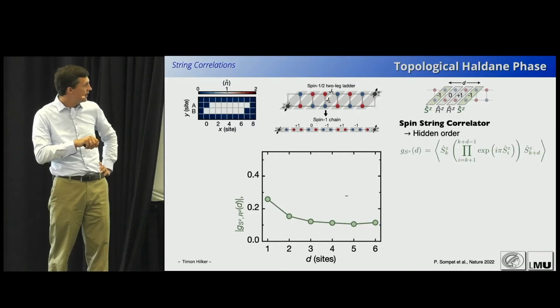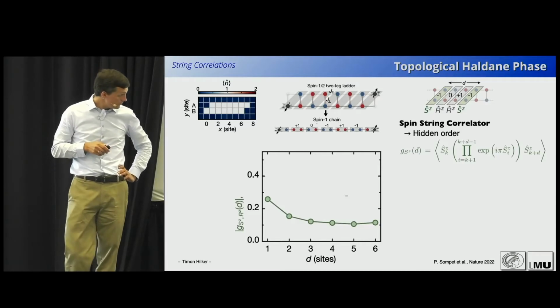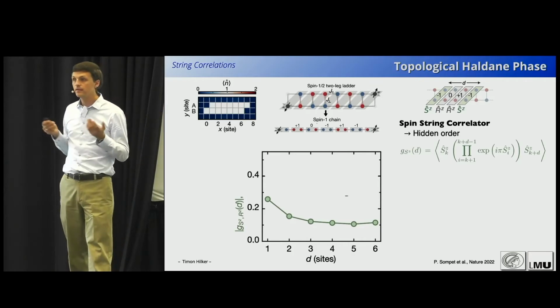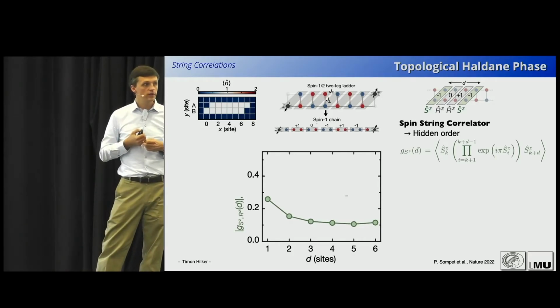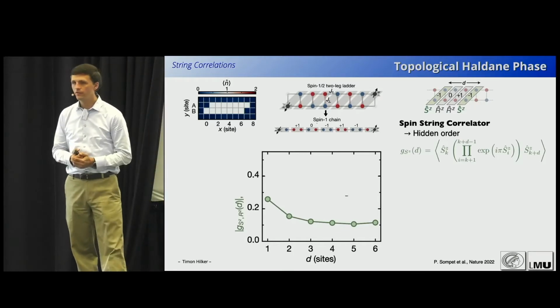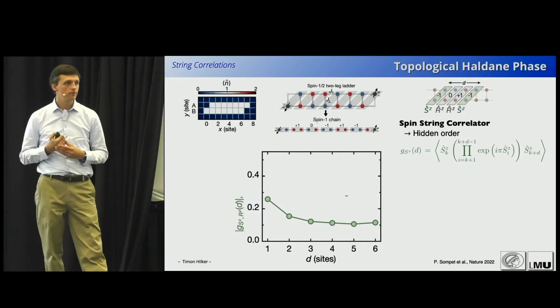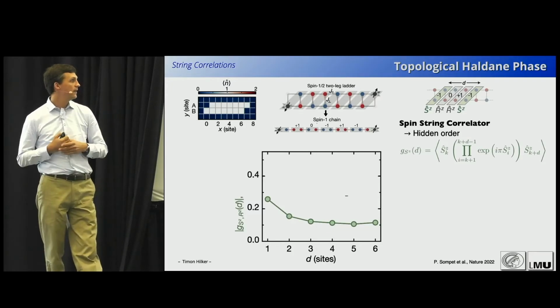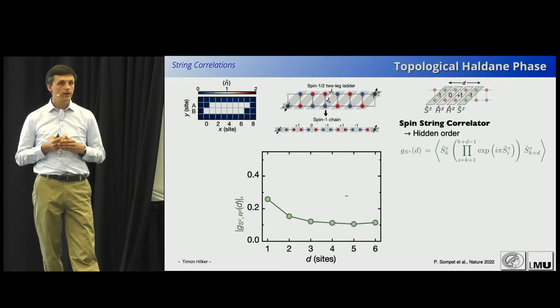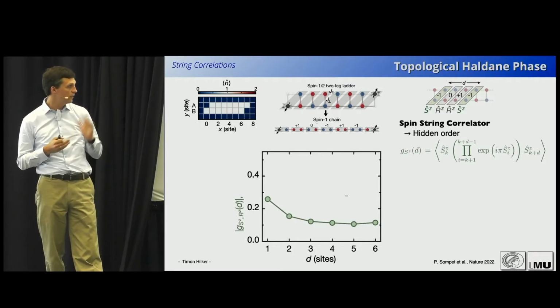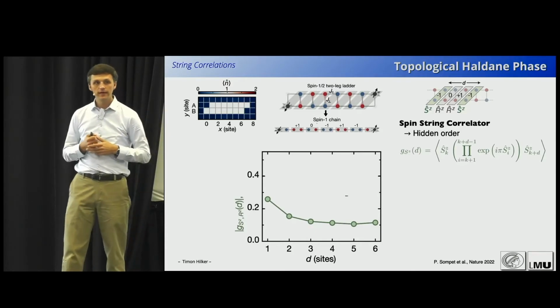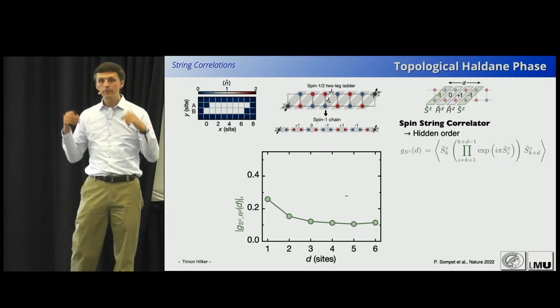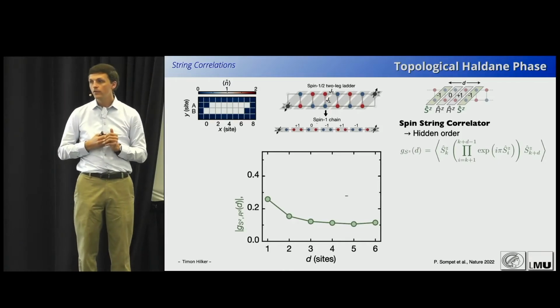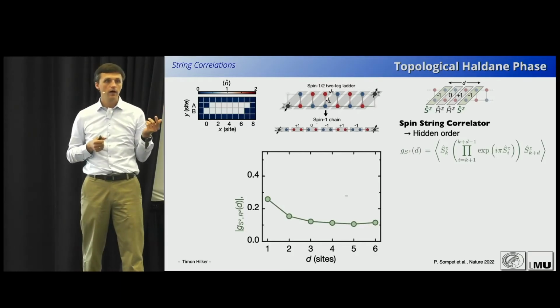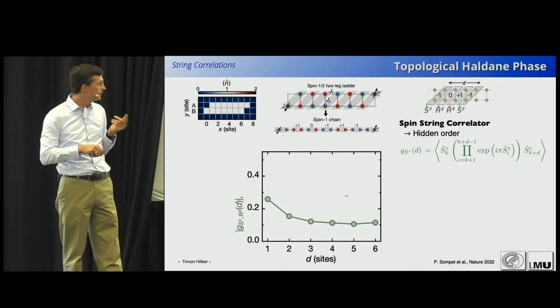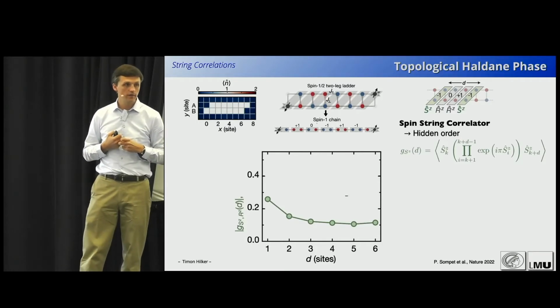And yes, indeed, we find a finite value over our system sizes, which of course, one needs to say is a finite temperature system, as I was saying before, so one can immediately expect a complaint that, oh, this is a phase that should only exist at 0 temperature, so how can there be anything at finite temperature? And then once again, the finite system size comes into play, because one can directly calculate in these systems of 7, 8, 9, 10 sites side length of this ladder that the overlap at our temperatures with the absolute ground state is still on the order of 50%. So basically half of the time we actually realize the ground state. And that means that we can still see these correlations which are only present in the ground state of the system.